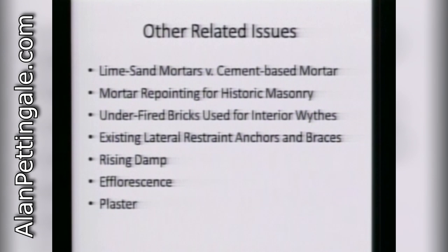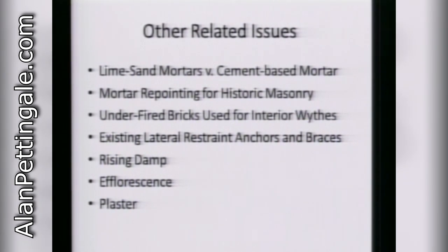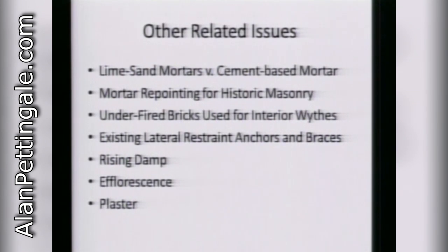When buildings were built originally 100 years ago, the methods of creating brick by heat in a kiln were much less efficient and uniform — wood-burning kilns produced much more inconsistent firing. So it was common practice to use the less-fired, weaker brick on the interior wythe, and the better brick on the exterior weathering face. This is important to know because if you're looking at a building on a downtown main street and one of the adjacent buildings had a roof collapse and was then demolished, what was an interior face is now an exterior face. You can have significantly aggravated problems if that's not protected properly.